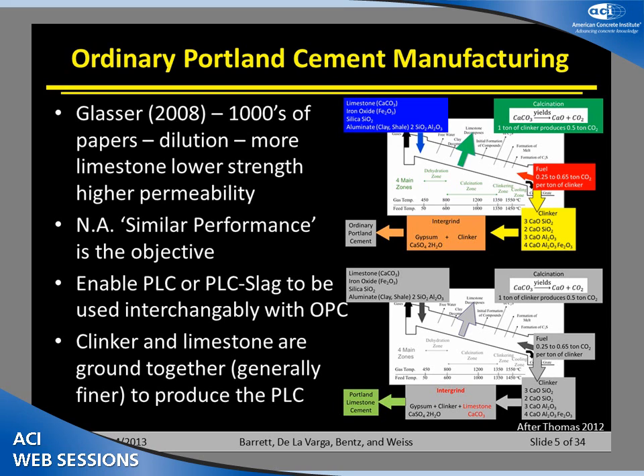But the whole idea here is instead of taking your limestone or your calcium carbonate and running it through the kiln, you can introduce it later on in the process. If you can intergrind it later on in the process, now you don't have to heat it up. Now you don't have to have that CO2 that's been given off through the calcination process. You can intergrind it and you can produce a Portland limestone cement.